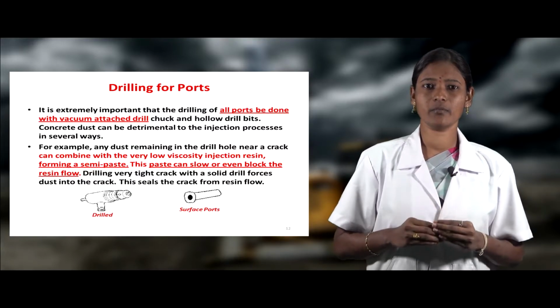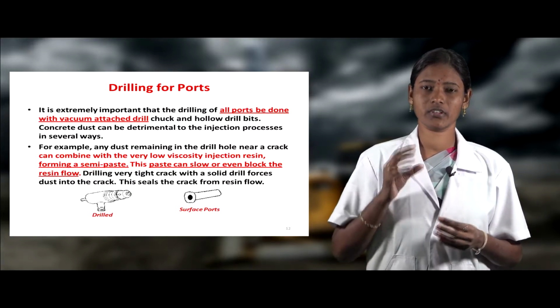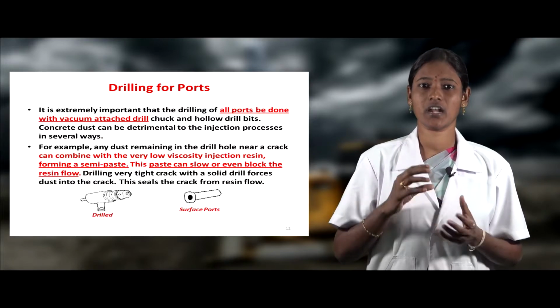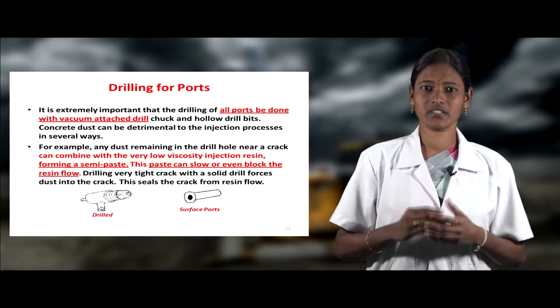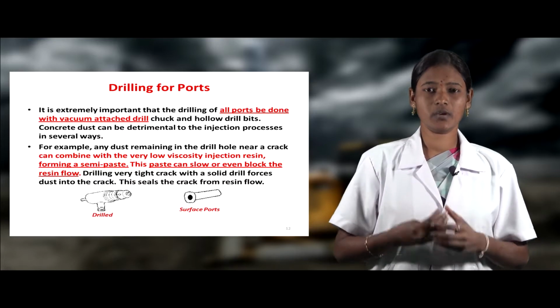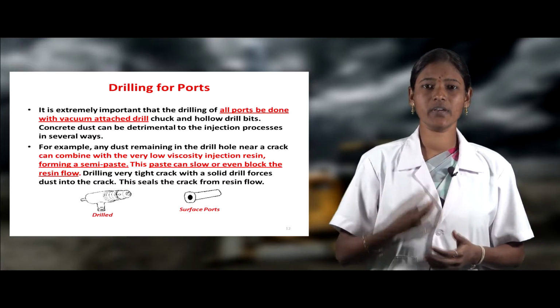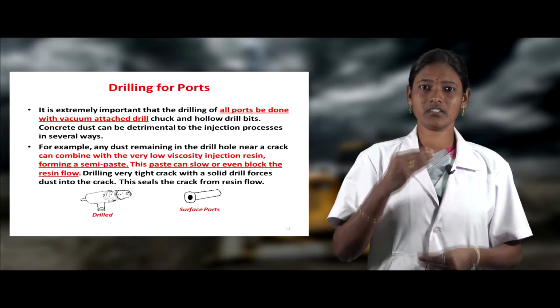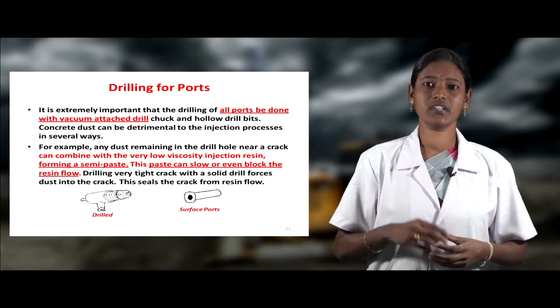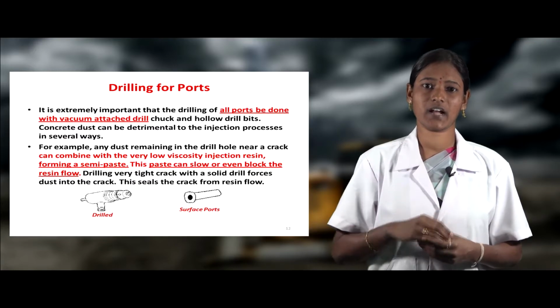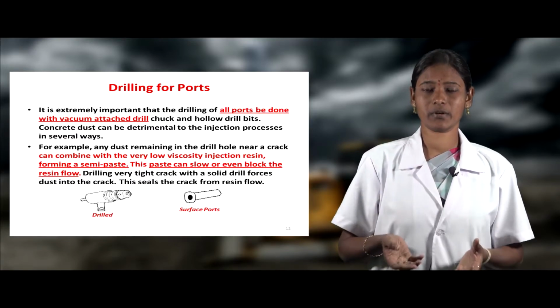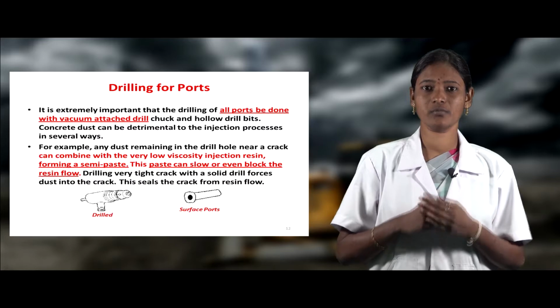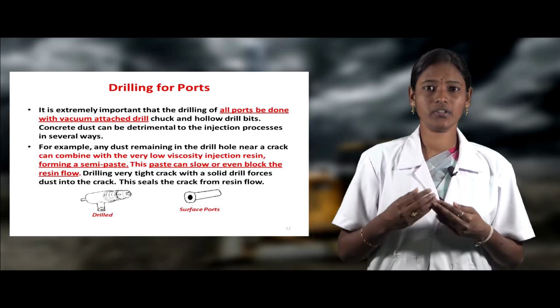It is extremely important that the drilling should be done with a vacuum-attached drill chuck and hollow drill bits. Concrete dust is the major cause that leads to improper filling of the resin, so it should be taken care of. For example, if dust remains inside the crack, it will combine with the low viscosity injection resin and clog the crack. These blocks will prevent the resin flow. So, drilling should be done carefully, removing the concrete dust.